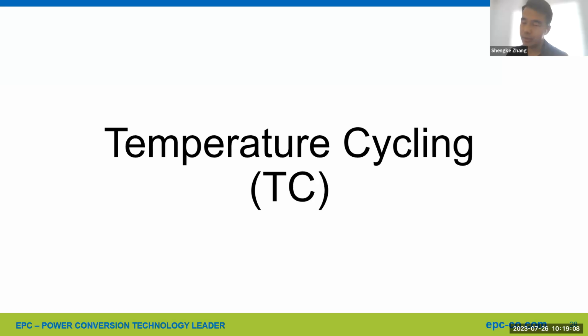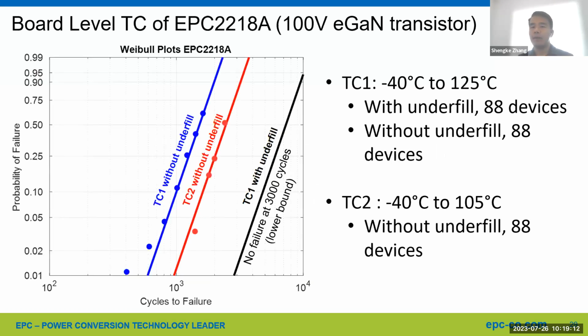So next and lastly is the temperature cycling, TC. Board level temperature cycling testing of EPC2218 was done at 2 different conditions, which are minus 40 C to 125 C and minus 40 C to 105 C. At the first TC condition, we tested 2 groups of parts, with and without underfill material. We generated another Weibull plot for 3 sets of temperature cycling data using our test-to-fail approach. Most importantly, underfill drastically improved the temperature cycling reliability of our chip scale package devices. As you can see on the right, for the black curve, we have yet to identify any failure to date at 3,000 cycles of minus 40 Celsius to 125 Celsius testing.